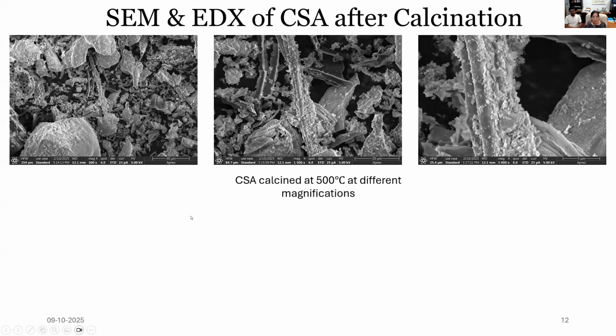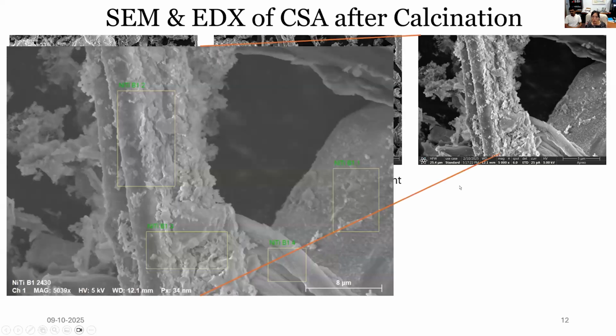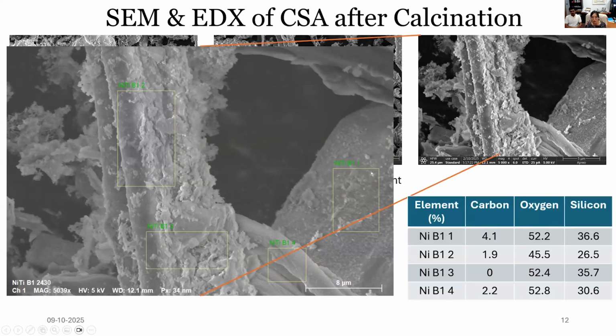So if we take a look at the ash calcined at 500 degrees from just water wash, we can see that you can still see the fiber structures of the material. And then if we enlarge, for this picture on your right, you actually see a lot of deposits on the surface of the material. So if we enlarge into that area and also do the EDS, we found that lots of these deposits are actually silica. Which gave us an important message: these materials actually have a great potential to be used as an SCM if they're treated properly.